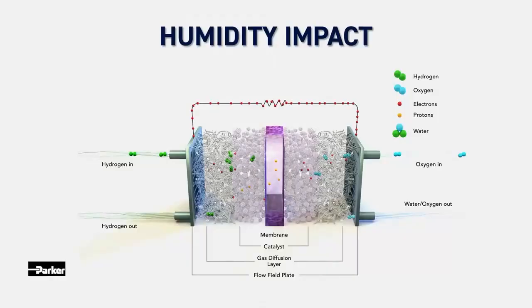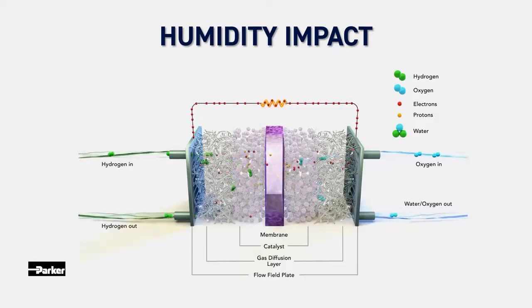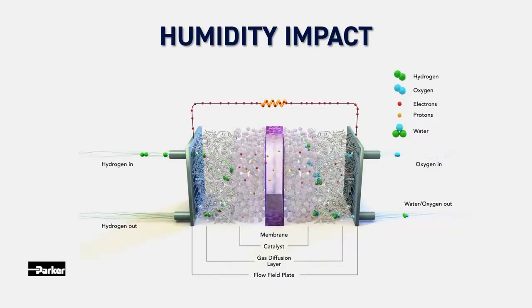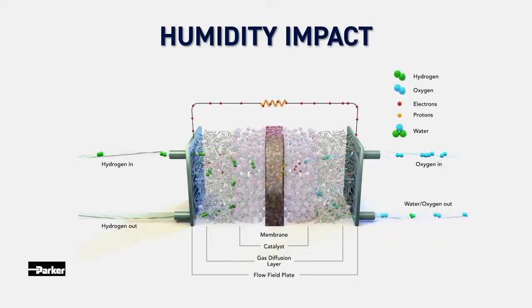So we looked at how different gases can poison the catalyst and impact the performance of the stack. Now we will take a look at how the humidity of the air impacts the performance of the fuel cell. The proton exchange membrane functions as a conductive electrolyte. The membrane needs to be humid to effectively transfer the protons and to block the gases from passing from one side to the other. If the membrane dries out, this will impact the proton transfer, and it will also reduce the durability and lifetime of the stack. If the membrane is not humid, this can damage the membrane itself.